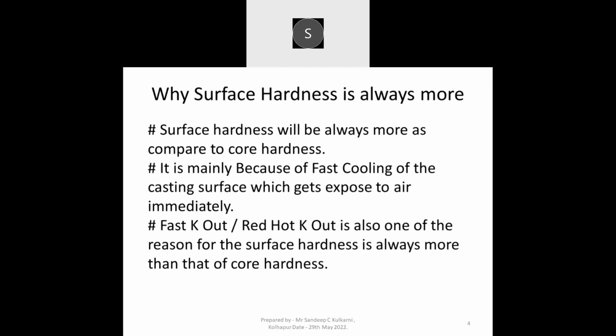Why is surface hardness always more? So let us understand now why the surface hardness is always more. Surface hardness will always be more as compared to core hardness. It is mainly because of fast cooling of the casting surface, which gets exposed to the air immediately after the box is knocked out. Fast knockout or red hot knockout is also one of the major reasons for the surface hardness always being more than the core hardness.